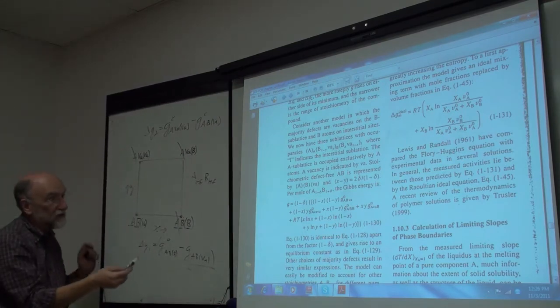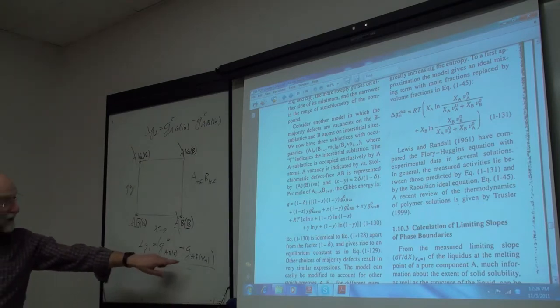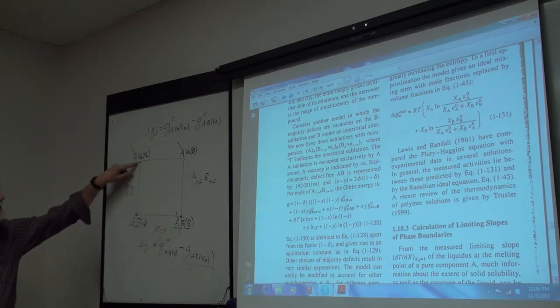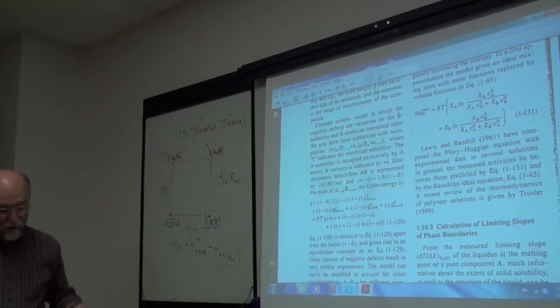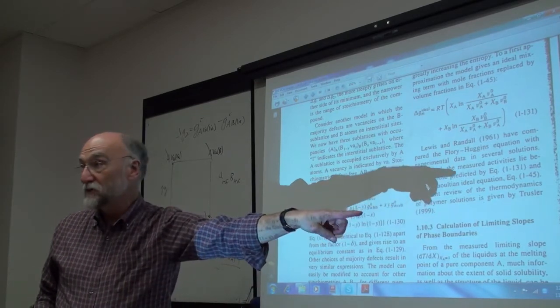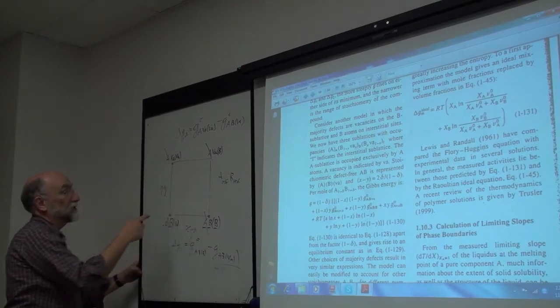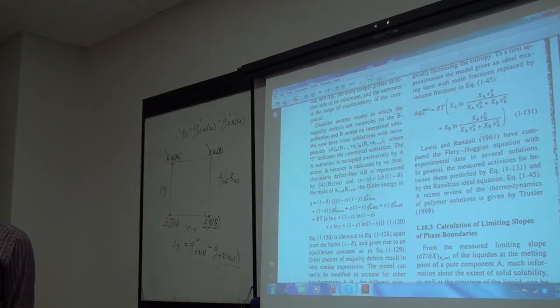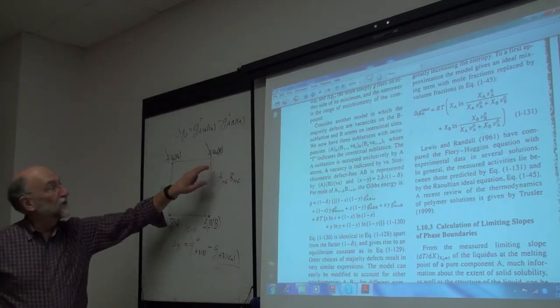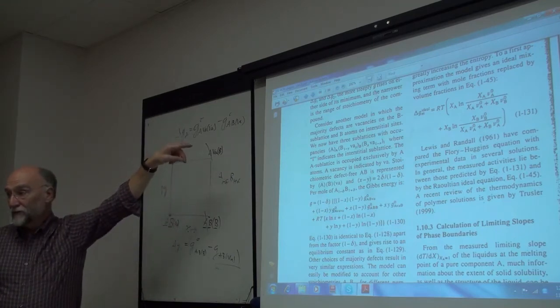So your model parameters, before in the substitutional model, the model parameter was the energy of forming a substitutional defect. Now it's the energy of forming an interstitial defect here, or the energy of forming a vacancy defect here. Okay, your defects are B lattice vacancies, and B's on interstitials. Okay, so your model parameters are still this minus this and this minus this, which are the energies of forming the majority defects. This thing up here should be the same thing. The Gibbs energy of this thing should be this plus this minus this, just as we did before.